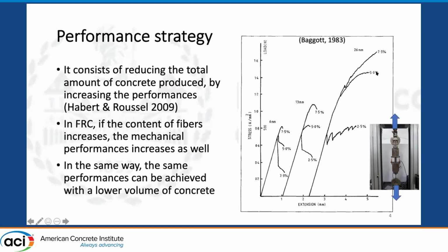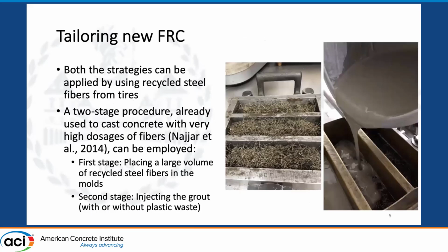So we doubled the content of fibers, and the strength as well. But the cost and the environmental impact are not doubled. So this is particularly convenient because we can reduce the mass of total concrete and the mass of carbon footprint of our materials. However, the cost from 2.5% in volume to 5% in volume of FRC increased, and so if we want to apply the performance strategy and also the substitution strategy, we can use recycled steel fibers because they are cheaper than the industrially manufactured steel fibers, of course.